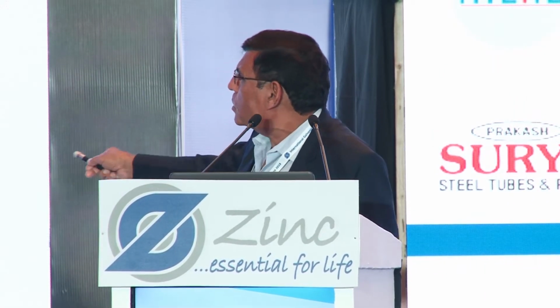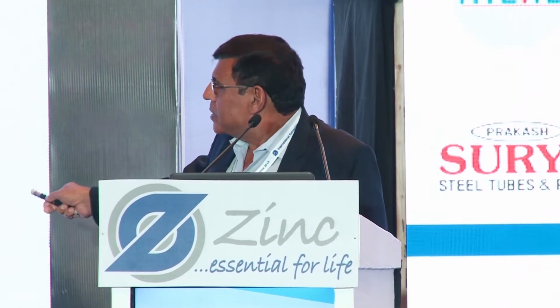So in this case, the amount of zinc is not more than 10 to 15%. And that is why when you make such a coating with epoxy or so, your life can go from anywhere from 6 months to 2 years. Okay? Now you increase the zinc concentration to around 70 to 78%. The most common organic zinc-rich coating is applied on every structure before the epoxy coating is done.